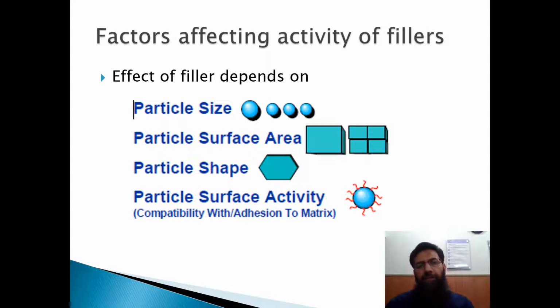These factors are very important in the selection of fillers for different parts, for different applications. The particle size is very important because there are different types of fillers available in our market, which are in the micron sizes or in the nano sizes. Just like the three main fillers in our industry, calcium carbonate, carbon black, and silica. Out of these three fillers, the calcium carbonate is mainly present in the micron sizes, whereas the silica and carbon black can be present in the nano sizes. The particle surface area is very important in terms of the reinforcement of the filler. Better the surface area, better would be the reinforcement of the filler with our polymer.